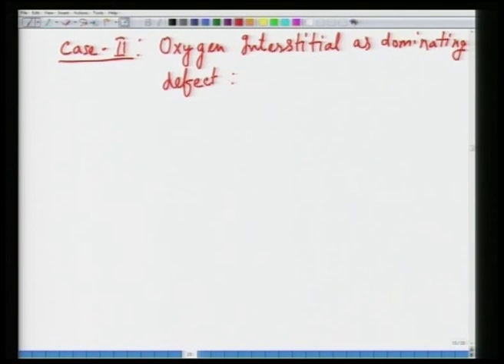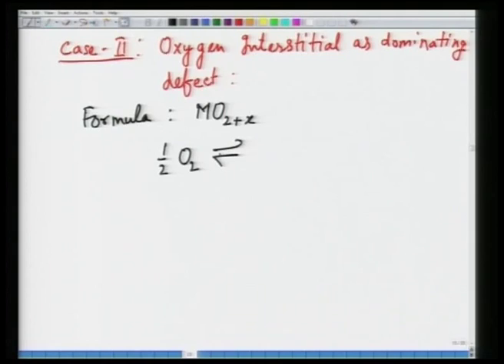So, in this case what happens is, now how do you represent these materials? So, formula would be MO2+X, since you have extra oxygen, and extra oxygen in another way means you have deficiency of metal, and the way this happens is half O2. So, here the oxygen does not go to oxygen site, rather it goes to interstitial site. If it goes to interstitial site, you do not need to create any kind of vacancy. If it goes to interstitial site and if it is completely ionized, it will have double dash, OI double dash, plus formation of two holes. So, again this would give rise to p-type conductors.